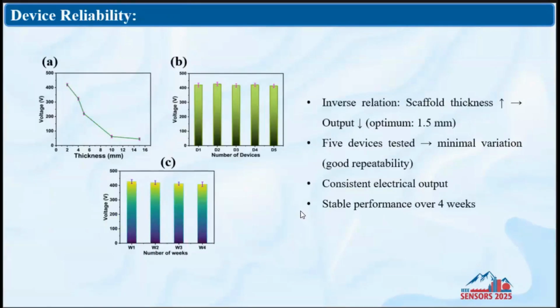Here is the device reliability. We tested different thicknesses of the silk thin film, and the porous silk structure also, and verified how the voltage varies. As the thickness of the silk scaffold increases, the voltage slowly drops. If the thickness increases, the mechanical force between the two materials is less, and the main problem is that it is not able to create a surface charge between the two materials.